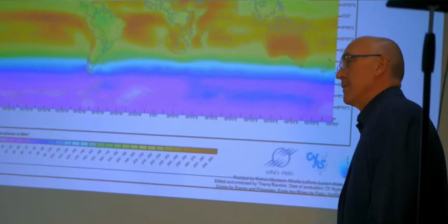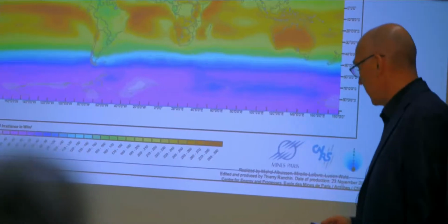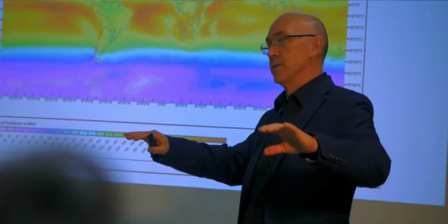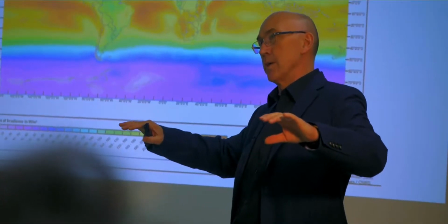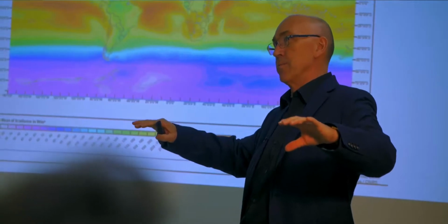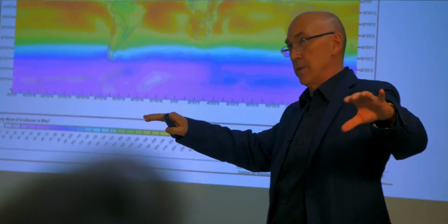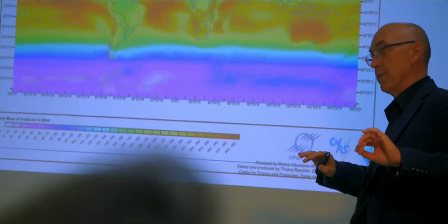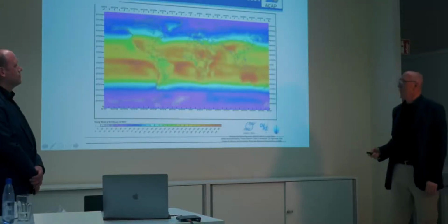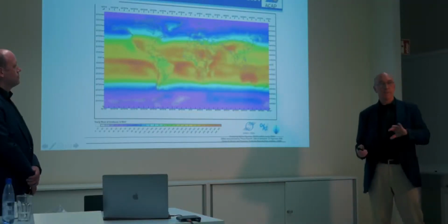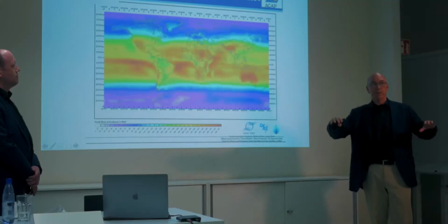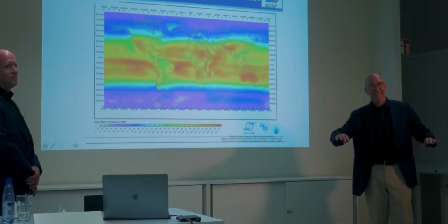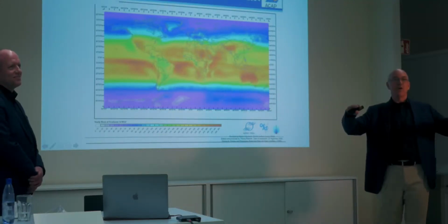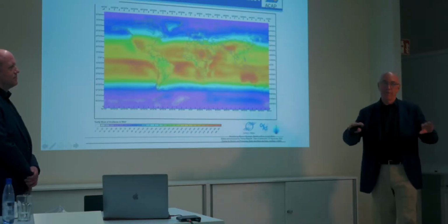We talked about that for a number of reasons. The other thing is that if you've got a solar cell which can float, then you can also, in hot areas, stop evaporation of ponds, lakes, etc. in theory, and therefore protect it in that way. Your water may get a bit hotter. And so people have looked at that, but of course then you have the secondary problem. You're putting it in one of the things you don't want it in, and you're basically putting it on top. And so you're going to have to be reasonably careful about what you do.